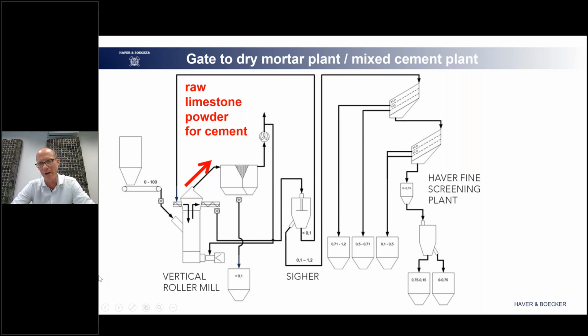so to reduce the minus 100 micron materials, and then by doing some fine screening inside a Haver fine screening plant, create the typical grades we need later on for our mixed cements and dry mortars, which are, for example, 100 micron to 300 micron, 300 to 600 micron, 600 micron to approximately 1 millimeter, however you and your customers need that. So that is a very, very easy link, which works, of course, with a vertical roller mill, but also with the roller presses, and also the ball mills, which have a different setup, but it is important to have a pre-sifted material to bring it into the fine screening plants.